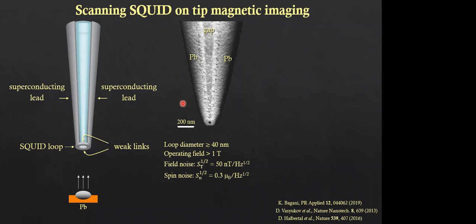On top of that, we used lithography to pattern the geometry of our choice. 40 to 50 nanometer was helpful in the sense that we wanted to go as thin as possible, but thinner than that we didn't try, I think. Limiting it to 40 to 50 nanometer actually decreased the momentum relaxing mean free path, and that changed how the hydrodynamic flow happens in the system.